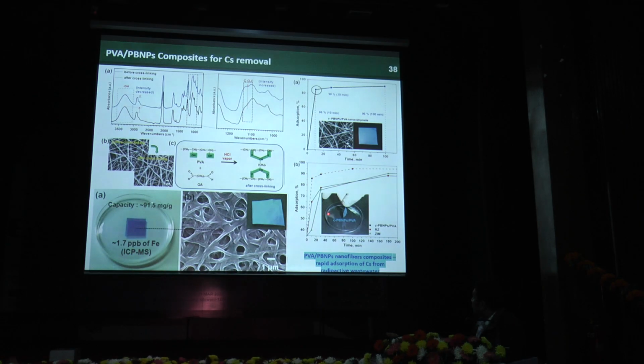And this result shows the absorption is over 90%, and within 10 minutes from the industry wastewater, when we use our material, 90% of the Cs can be removed. So this is highly advantageous.